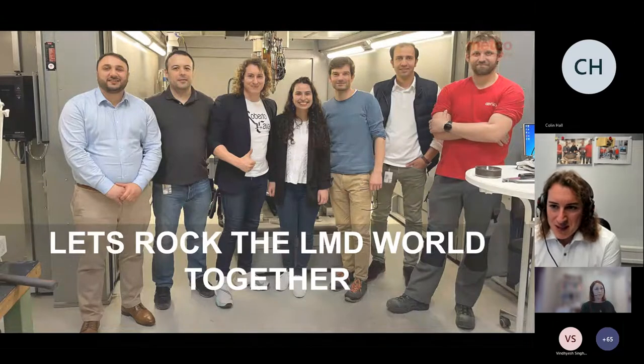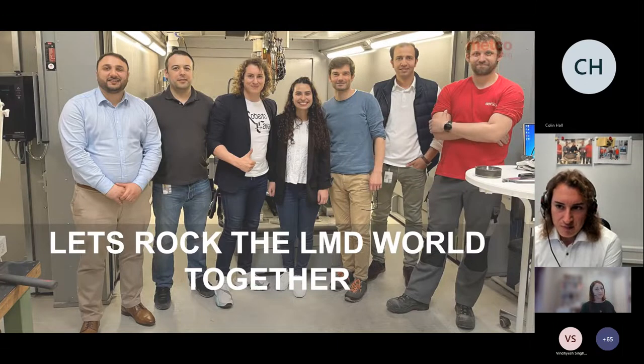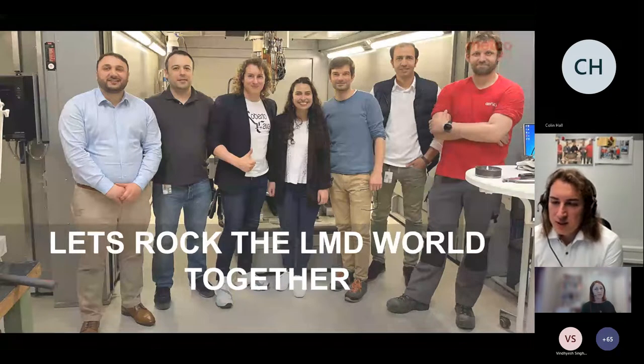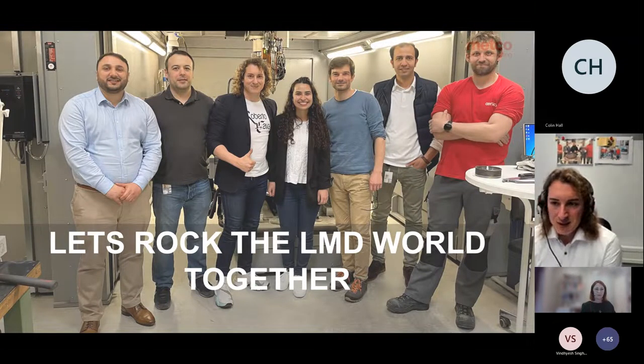Well, pure ceramics, I personally read a couple of papers where people claim that they have done it and this is working. I have never seen that on an industrial scale so far, but I'm always open to learn something new. However, to bring ceramics to a melting and then extremely fast solidification without embrittlement, it's very hard. What we do is typical metal matrix composites, where you can use ceramic particles as a reinforcement of your metallic matrix, and in this case, this is working.